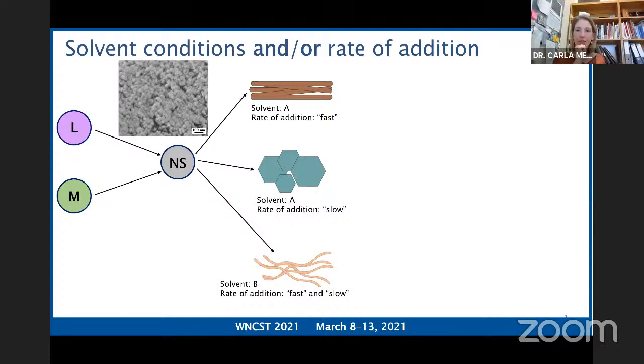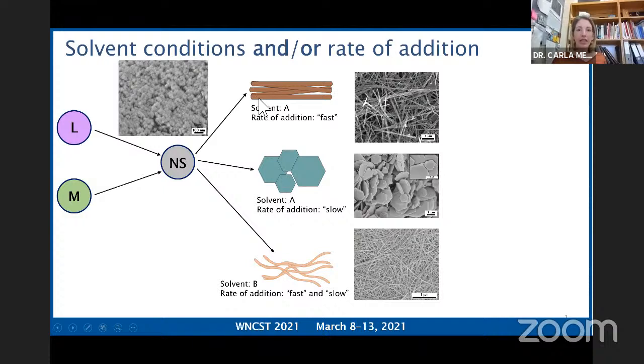In fact, I can show the pictures there. Simply with a difference in one case, if we use a solvent A, we'll call it, and we add microemulsion 1 to microemulsion 2 very quickly, that is, just immediately mix them together, we get the formation of these beautiful needles. When we use the same solvent, but the rate of addition is slower, so this is over the course of a minute, or over the course of an hour or hours perhaps, we get these beautiful hexagonal nanoplates. So again, the only difference being the rate of addition in this case. And when we use any old rate of addition, whether fast or slow, if we change the solvent within the microemulsion, we get the formation of these long, as we affectionately call them, noodles.